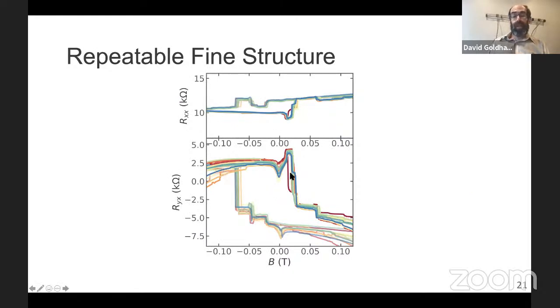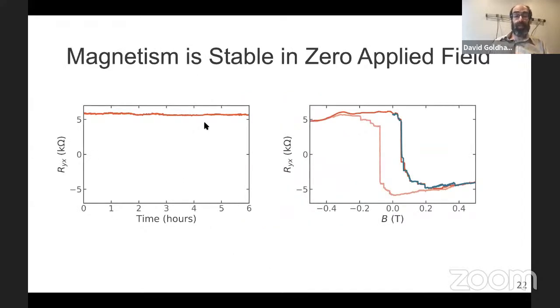If we go around in magnetic field in a loop multiple times, you can see that the structure is quite reproducible, and these steps are not just noise. They're likely, as I said, flipping of domains that occur consistently at particular magnetic fields. The magnetism is stable if we don't apply a field. So if we do a hysteresis loop, come back to 0, and then wait for 6 hours, the Hall resistance doesn't change, and then we can keep on sweeping, and it's as if we never stopped. So this magnet is quite robust at these low temperatures.